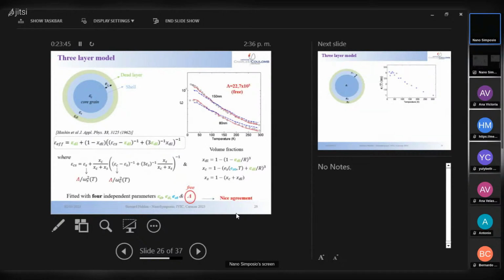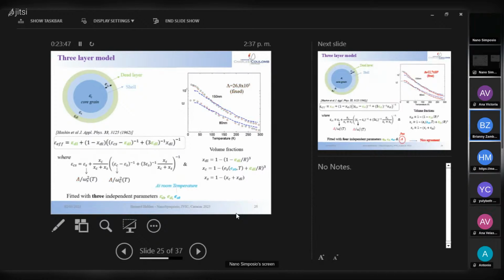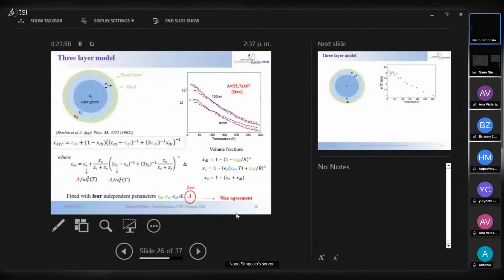And if you do that, you find this blue dashed line here, which is not bad, with only 3 parameters with the data. And if you free this parameter, which is the constant of the relation between the permittivity and the frequency of the mode, if you leave this free, it moves from 26 to 22, and you see you have the red curve, which is almost perfectly matched with the experiment.